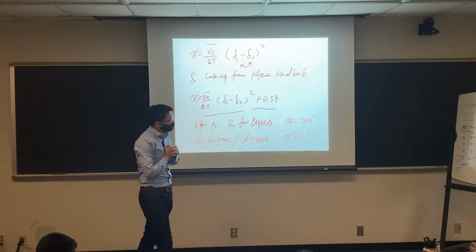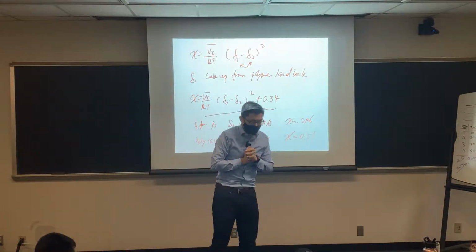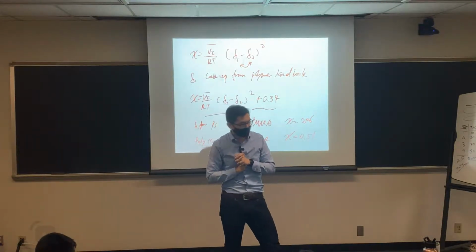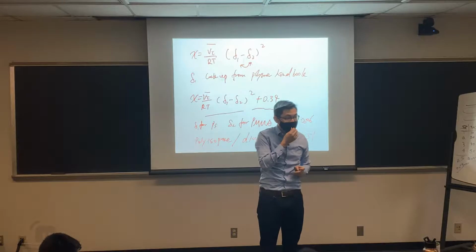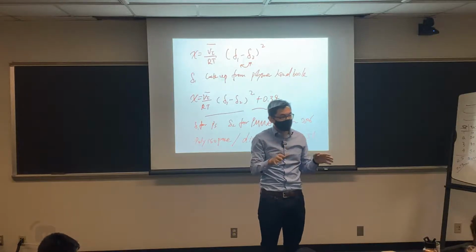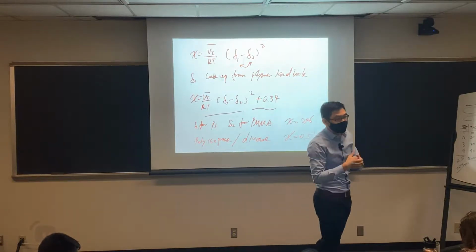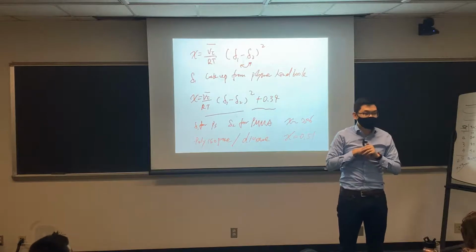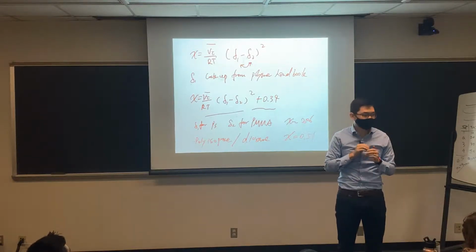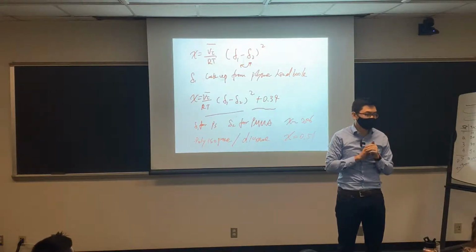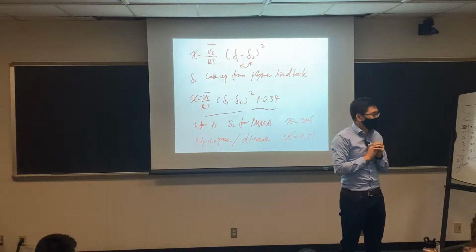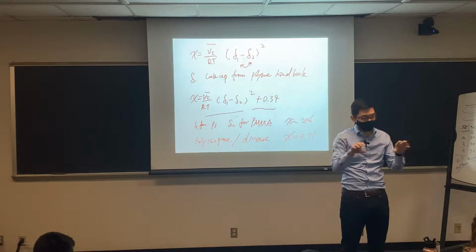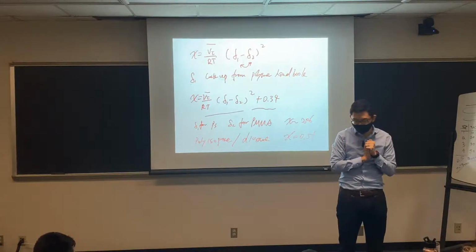This is a pretty good way to estimate the chi parameter based on the solubility parameter. As I explained, the solubility parameter originates from the fact that you need to look at cohesive energy density, how easy it is to vaporize and break the bonds in a given molecule.